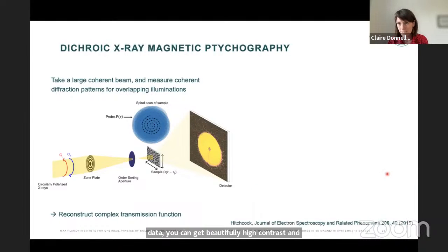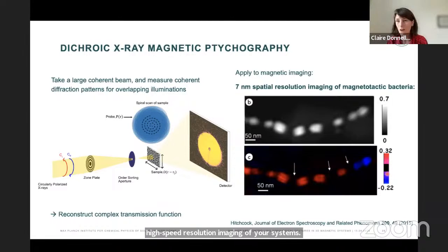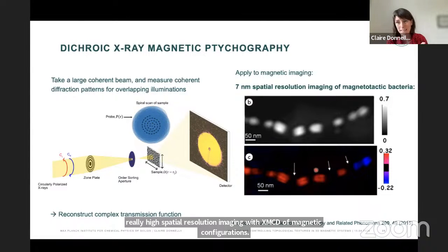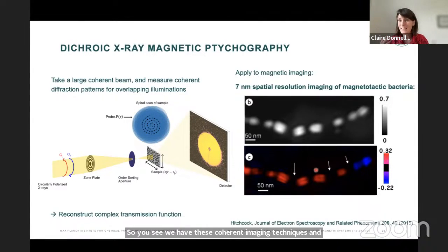And indeed, up until I think very much last year, where there was some holography work that overtook it, one of the world record demonstrations of high resolution magnetic imaging with X-rays was held by this ptychography technique. So you can see in this magnetotactic bacteria that you can achieve really high spatial resolution imaging with XMCD of magnetic configurations. So we have these coherent imaging techniques, and so far what we know is that they give us really high spatial resolution.